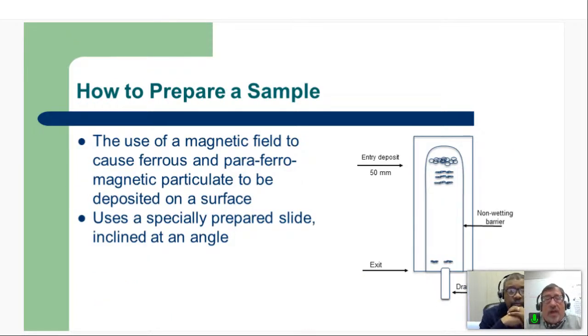First, though, we have to create the slide. It's a glass slide, and it's created over a magnetic field. So we use a magnetic field that's generated by two large permanent magnets that are separated by a thin separation of aluminum that creates this strong magnetic force, and that force creates a field that comes up through the glass. So as we put oil, a combination of oil and a solvent together, and flow them down across this slide, it's going to subject it to that magnetic force and arrange it and capture those particles in these specific lines. Now, how does that work?